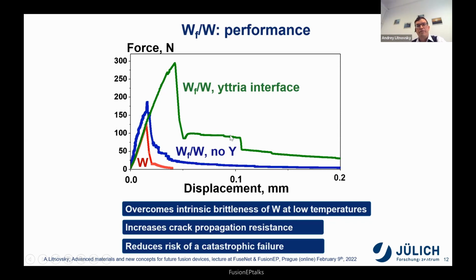And you can see here before the first big crack formation, the material is actually still expanding and going step by step and not going really to zero force. Which really shows the perfect pseudo-ductile behavior, and we see that this material really overcomes the intrinsic brittleness of tungsten at low temperature.